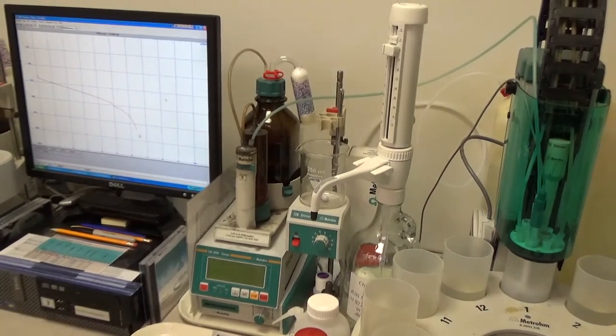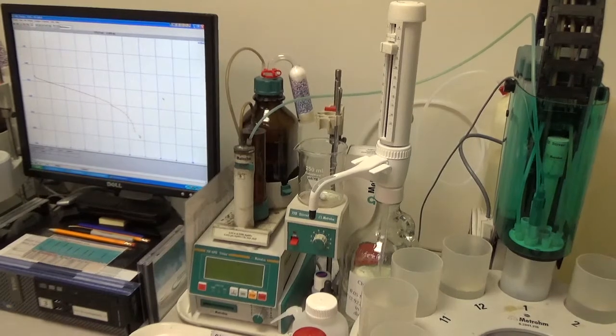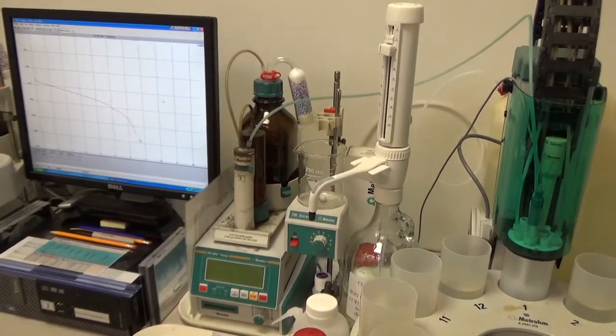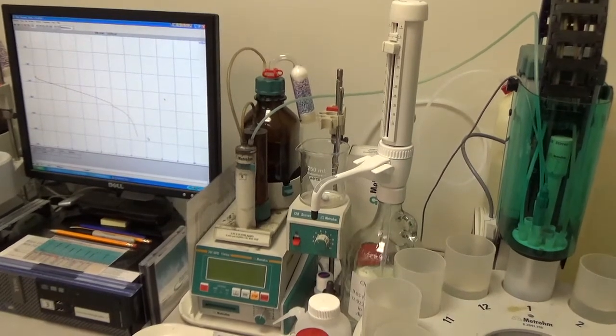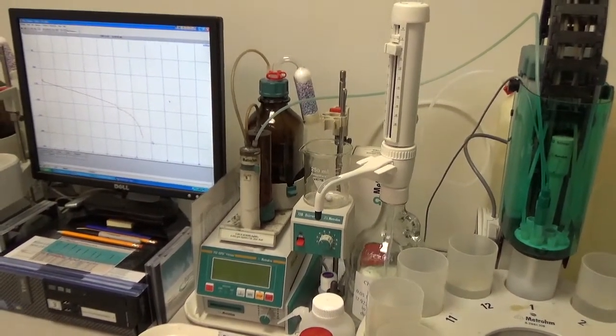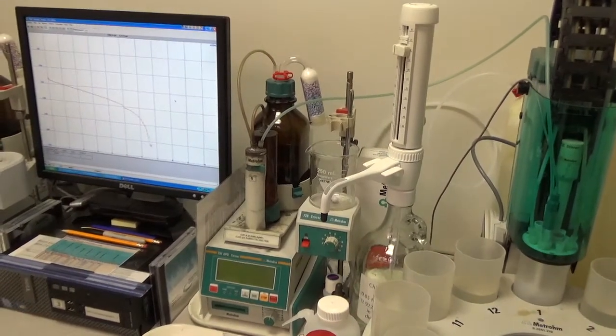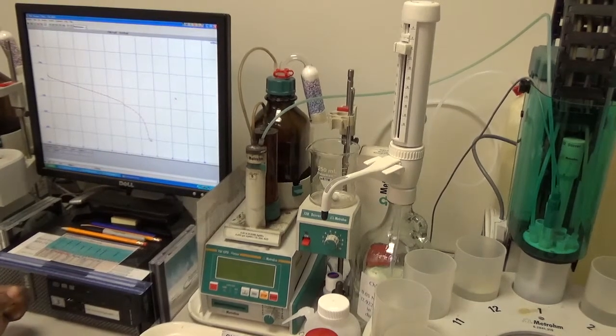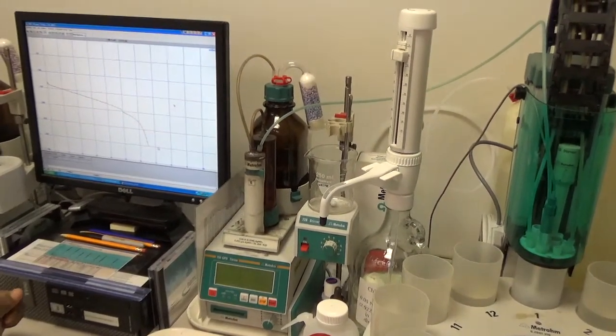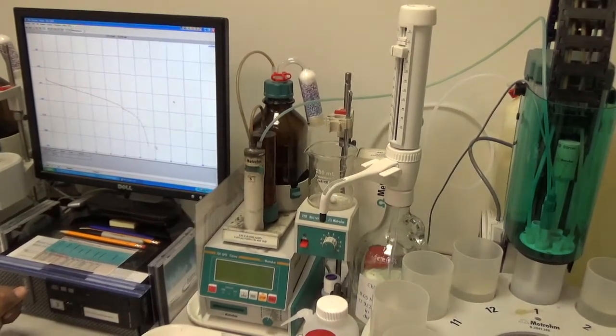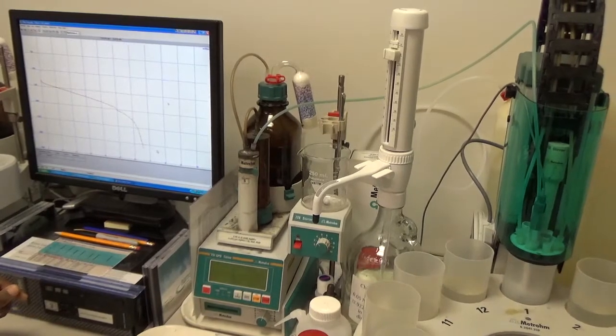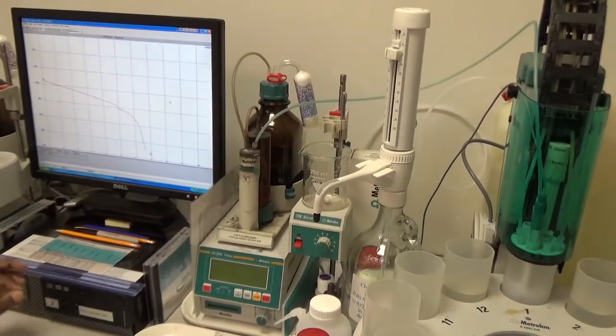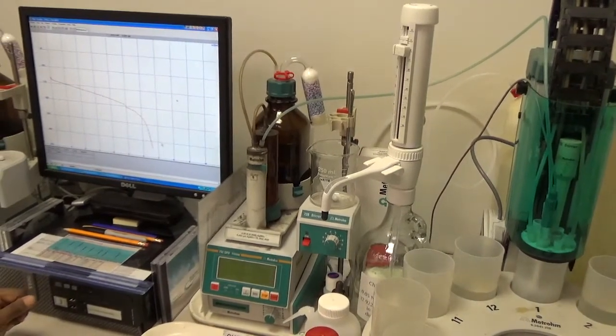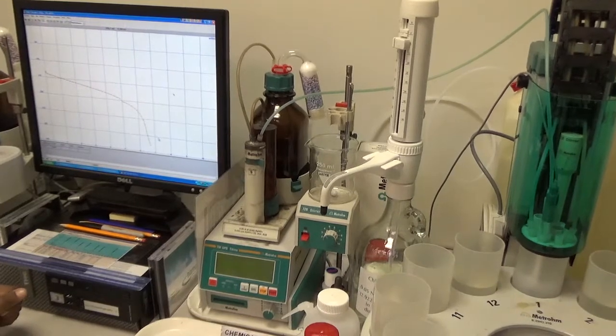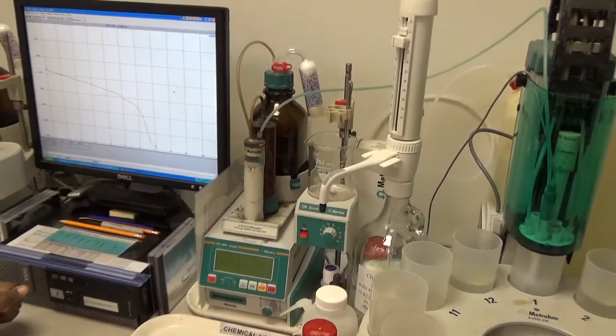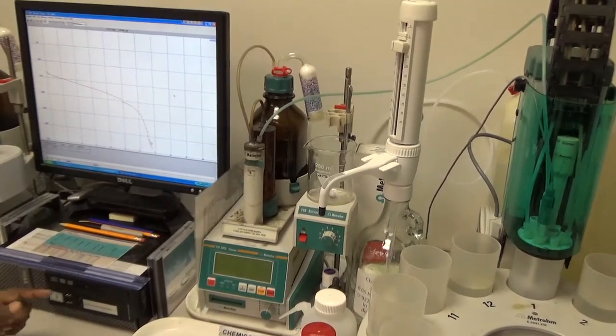So here it's showing how the curve is changing to steep. And as it approaches the equivalence point, it slows down the dispensing of silver nitrate. It's going to come pretty soon. And the equivalence point is shown by a circle on the plot. As soon as it finds the equivalence point, the titration stops. It goes a few milliliter more and then it stops. It goes about 2 milliliter more silver nitrate addition after passing the equivalence point.